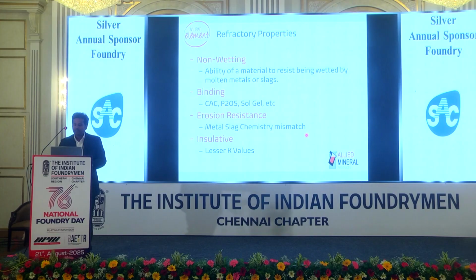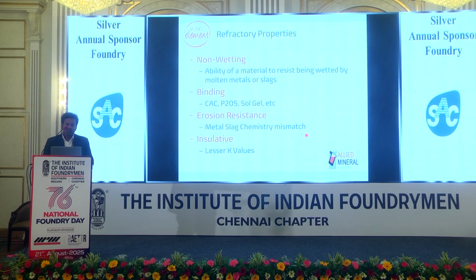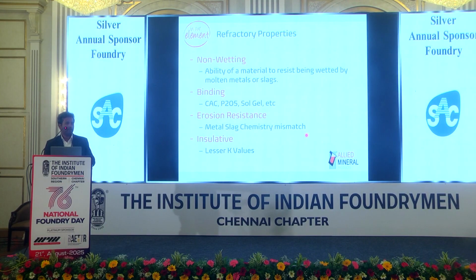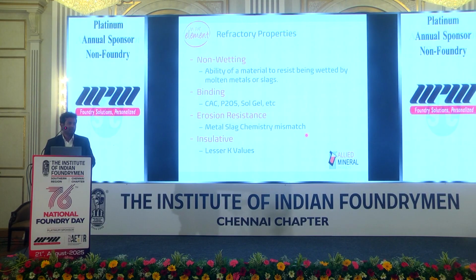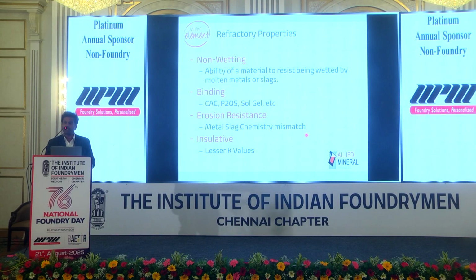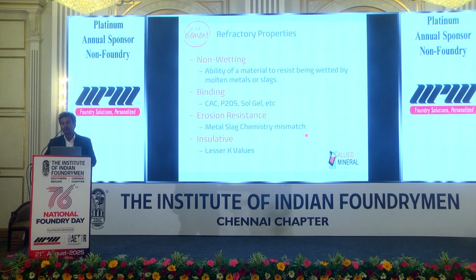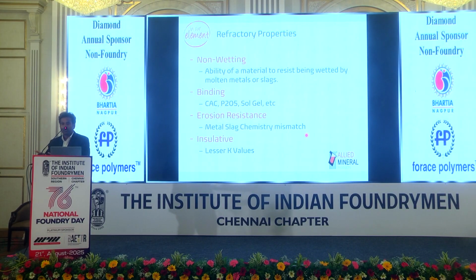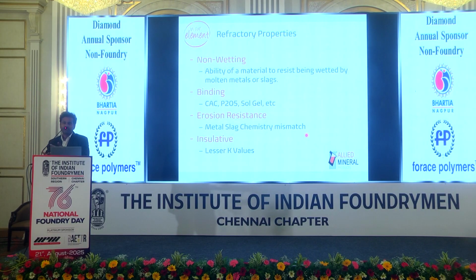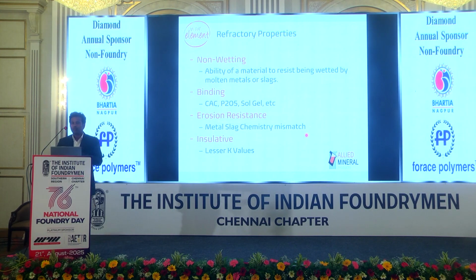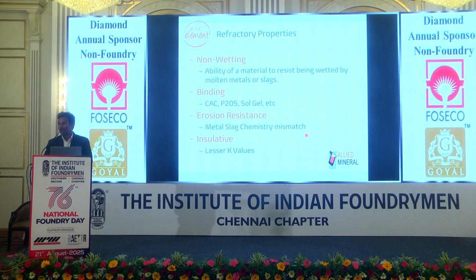And another property is erosion resistance. Your refractory should not erode either in a chemical way or a mechanical way. If you are using a bigger ladle, like 5 or 10 ton capacity, the liquid metal stream will be falling from like 3 or 4 meter height. So the bottom of your ladle gets eroded faster, and your refractory should have better erosion resistance.